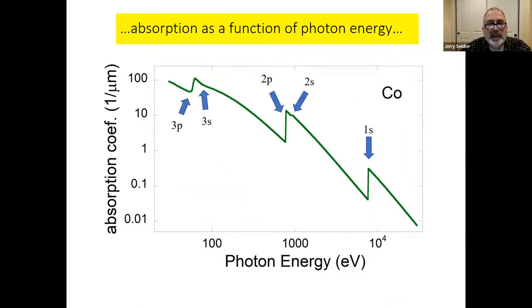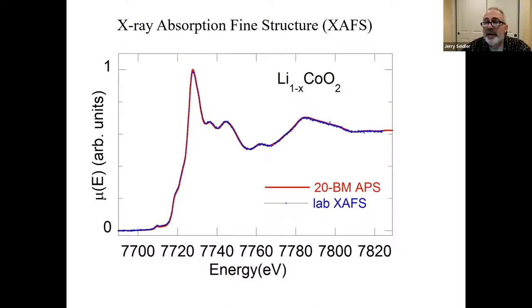If one looks from on high at the X-ray absorption as a function of photon energy, this is, of course, the photoelectric effect. And so you see the sudden onset of increased absorption whenever you pass the binding energy of an atomic shell. And if you look very closely at one of these absorption edges, as they're called, you see that there's fine structure. There's oscillations due to interference of the photoelectron wave function scattering off of neighboring atoms.